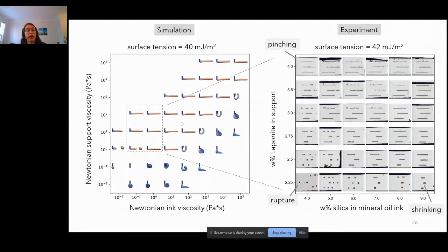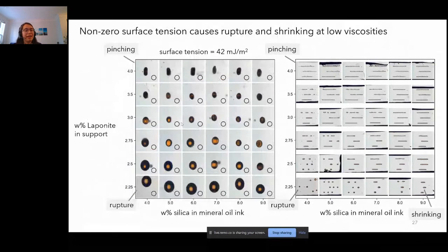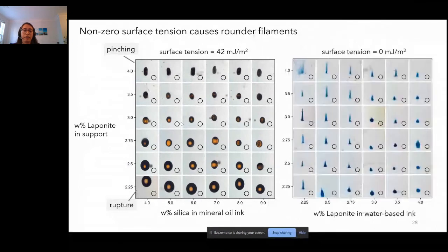If we go to high support viscosities, we suppress that breakup and we still get continuous filaments. However, they are pinched. So if you look at the cross-section of these filaments, they're a little bit taller and narrower than the circular cross-section that we're looking for. So that pinching is the same sort of pinching that we saw with our water-based inks, where we have tall and narrow filaments that occur at high support viscosities.